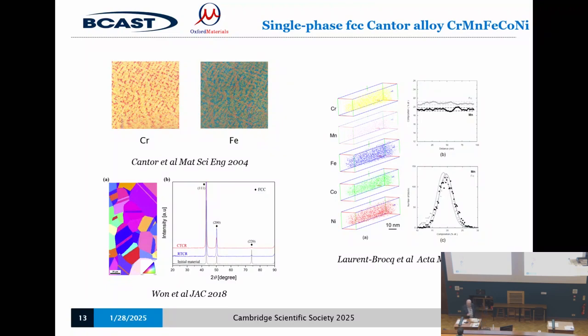And just to make the point, it really is completely random. These are atom probe measurements of the chromium, manganese, iron, cobalt, and nickel in a block. So each of these points here is an atom that's been pulled off the material, and you can see how they're distributed through. I mean, you can't see the crystal structure, but otherwise you're looking at atomic level, and you can see they're distributed, as far as we can tell, completely at random in this material, and that was a complete surprise.